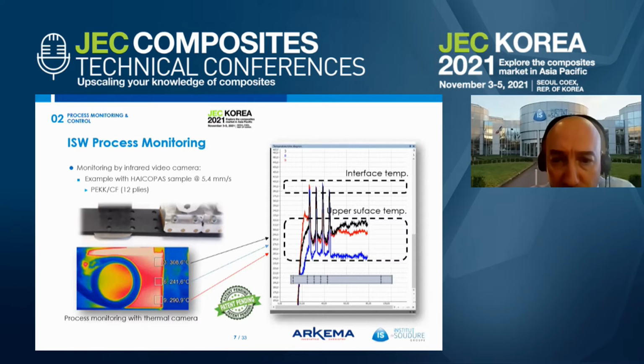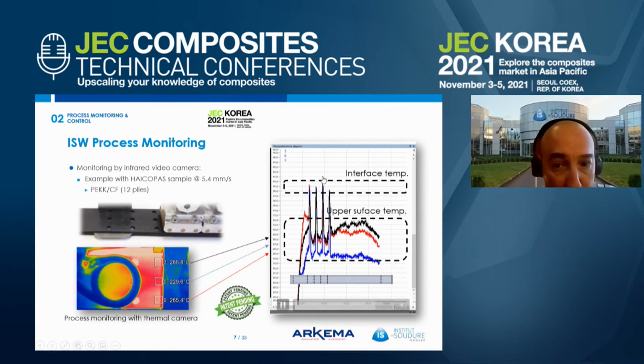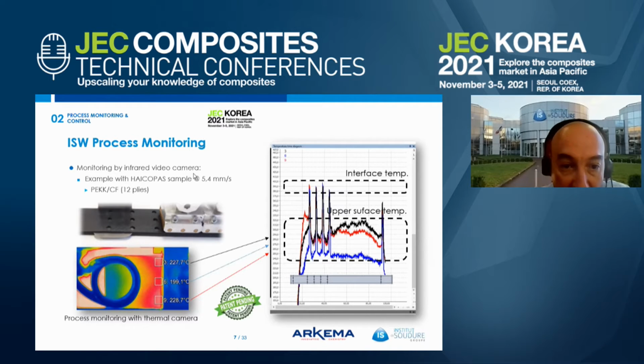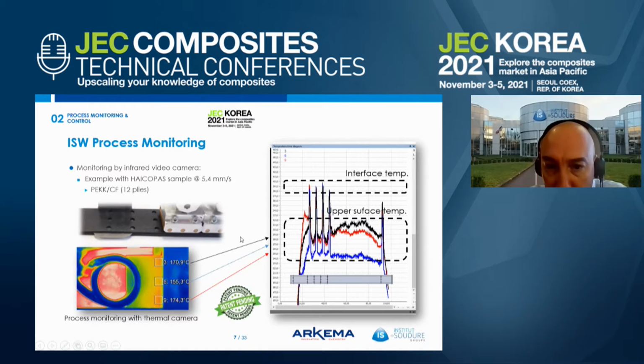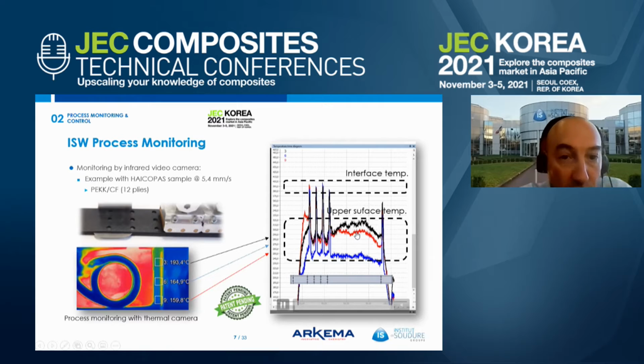So we can monitor and adjust the parameters in order to induce and to generate a good melting at the interface. If we have a look on the plotting of the temperature, we can see that, of course, when we are facing a hole, we have access to the interface temperature that is higher than the melting point of the thermoplastic. And when we are facing, I would say, a solid surface, not in front of holes, we have access to the surface temperature, meaning that we are way below the melting temperature and we are not affecting the full component, meaning we are not decompacting and generating defects in the substrate. So this is one of the main characteristics of the technology.